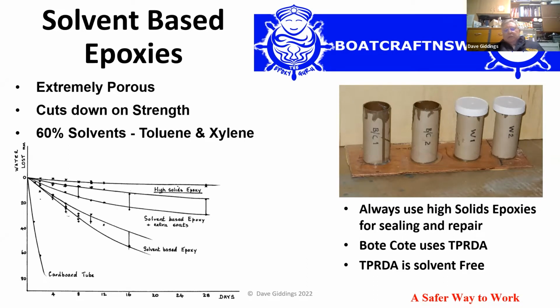And what it is, you then fill the tubes with water and put a lid on them. And over 20 days, the solvent-based epoxy had lost 60% of the water. It leached through the walls of the cardboard tube. The high solids epoxy, which is the line at the top, no appreciable amount of water gone.